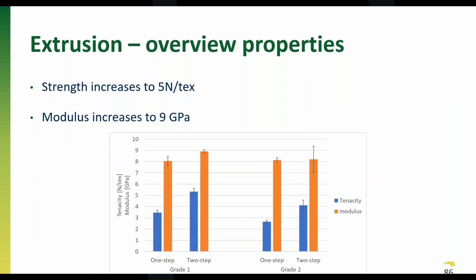Then towards the mechanical properties, strength, as I already mentioned, increased up to 5 Newton per tex. That's here in blue in the curve. Same again, two different grades, both in one-step and two-step drawing process. And the modulus is in orange. And we can also see that that increase is not that spectacular, going for one grade from 8 to 9 gigapascal. For the second grade, we remain a little bit constant around the 8 gigapascal, but the tenacity is the part where this two-step drawing process really has its benefits, increasing from 3.5 to over 5 Newton per tex for the first grade. And for the second grade, we go from 2.6, 2.7 to the 4 Newton per tex, which is also the requirement.